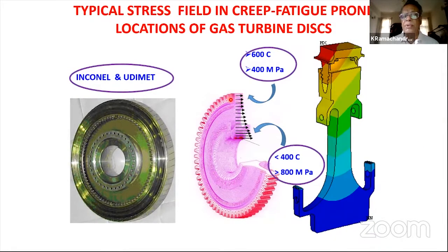In spite of the stress concentrations there, the stresses there are quite low, 400 MPa typically, for example, whereas the temperatures could be as high as 600 degrees centigrade, or even 700, 720 degrees centigrade, depending on the type of combustor that we have. Whereas the rim is very creep critical, because high temperature and long duration of exposure make the rim very creep critical. Creep deformation takes place there.